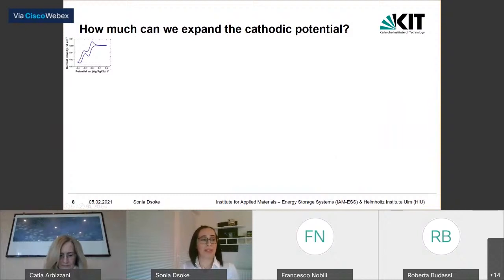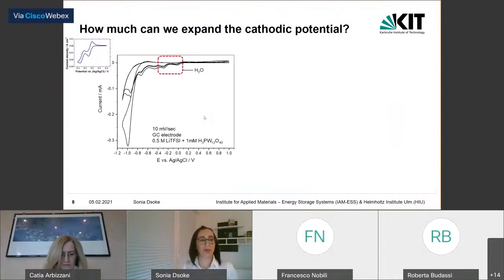However, the system was run in water, and we know that if we try to push the potential to lower values, you can observe here that you have an irreversible reaction, you have hydrogen evolution. In this same range, you cannot observe anymore the returning oxidation peaks. The system is becoming irreversible.